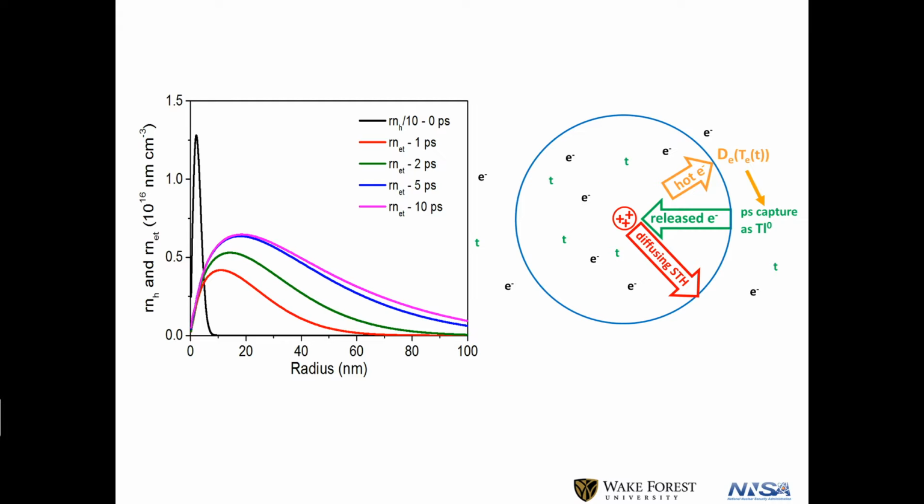So the hot ones go zooming out with their characteristic hot electron diffusion coefficient. The electrons, if they still survive and are not captured, many of them are, after 4 picoseconds now they see that electric field, and here they come, rushing back. But there are very few of these because most of them are captured with that really high capture rate. And then finally these holes, self-trapped holes, can diffuse outward, but that's your microsecond. Anyway, that's your slow process. So it's that kind of thing.